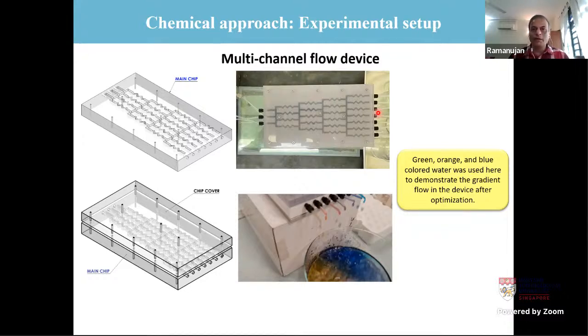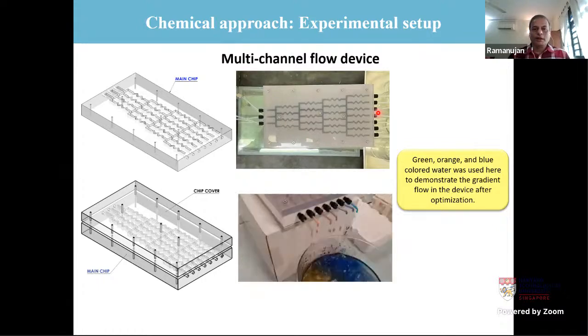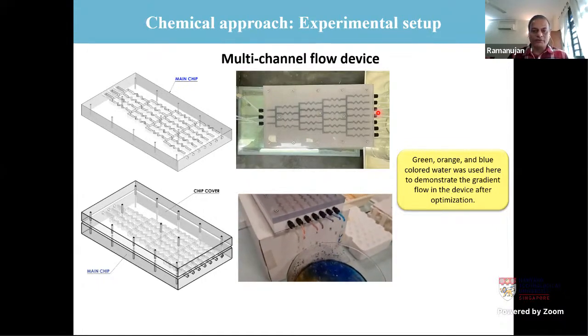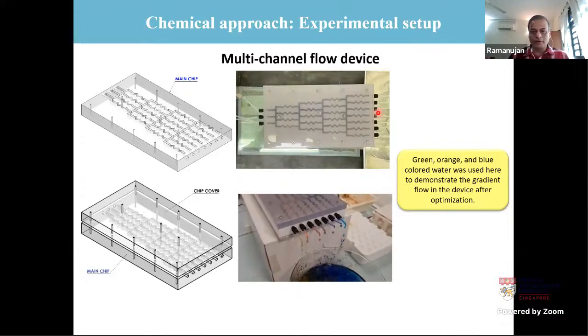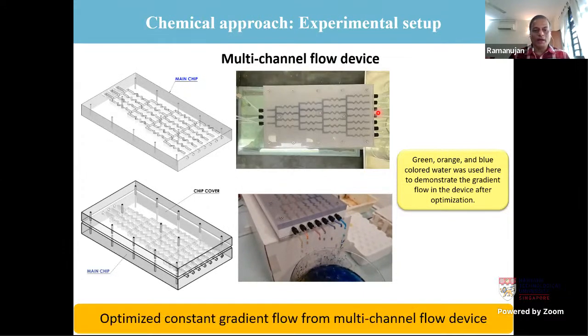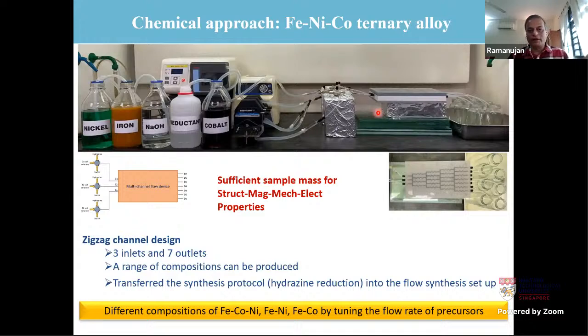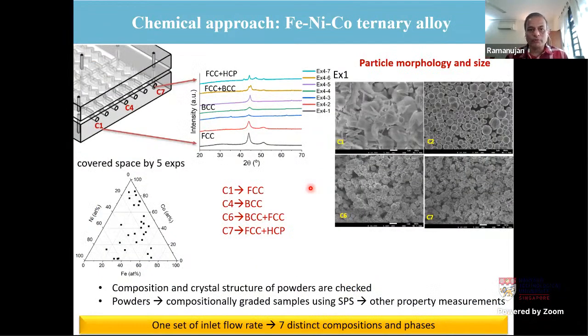So now we have the powder produced by this chemical method. And you can see here that it's pretty fast. We can produce different powders. And once we have these powders, this is the entire device. We can make enough sample for measuring mechanical properties. In the past, people had done this kind of work, but there was insufficient sample mass to measure mechanical properties. In our case, because this is a high flow rate, we can produce sufficient mass to also conduct mechanical property measurements.